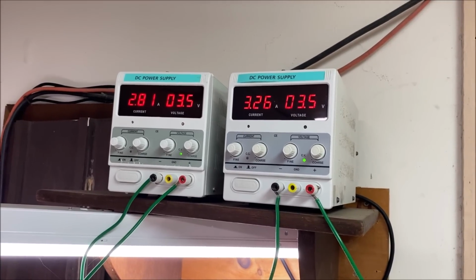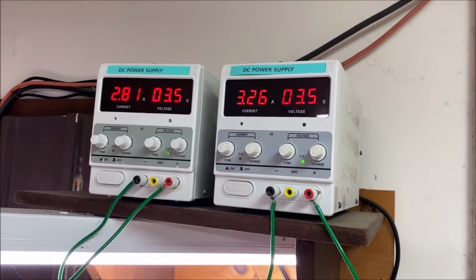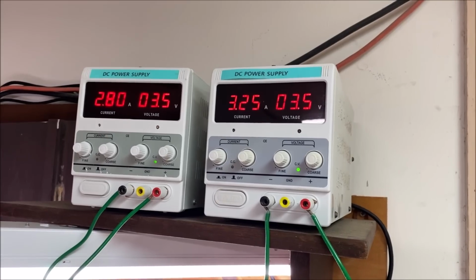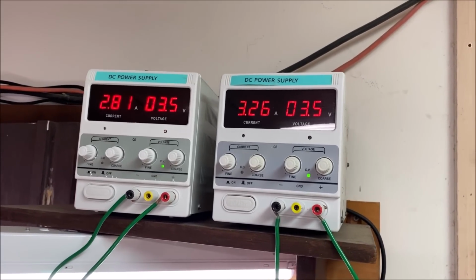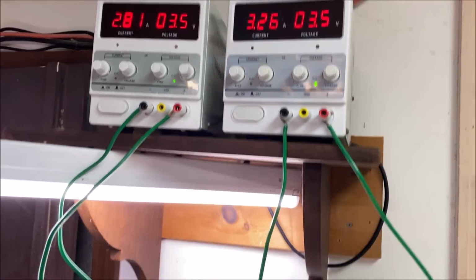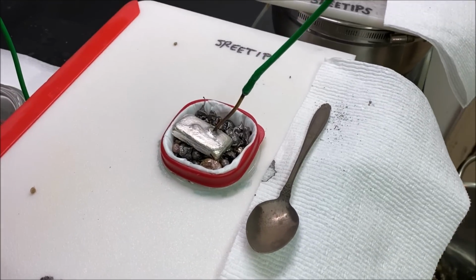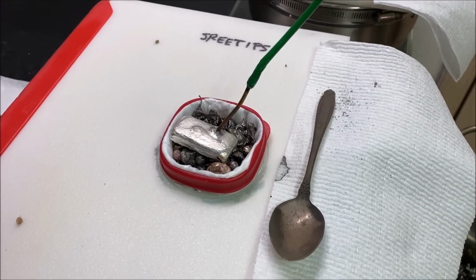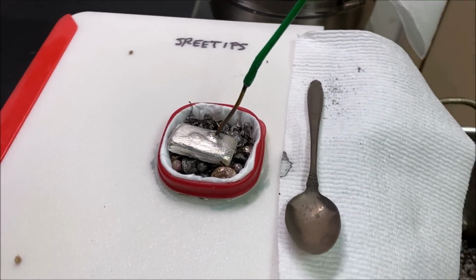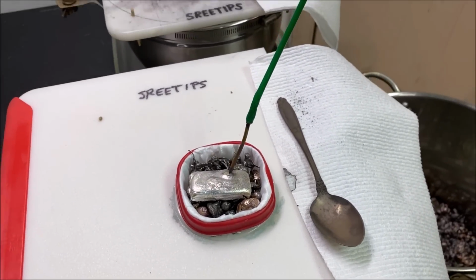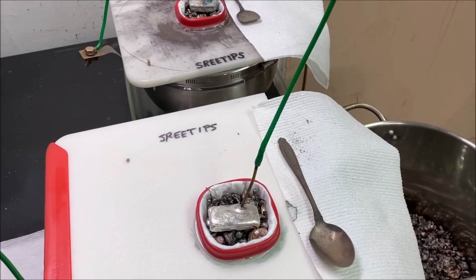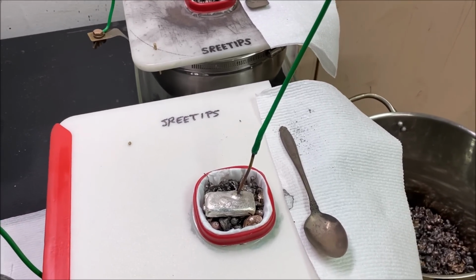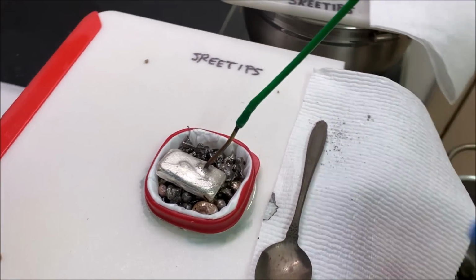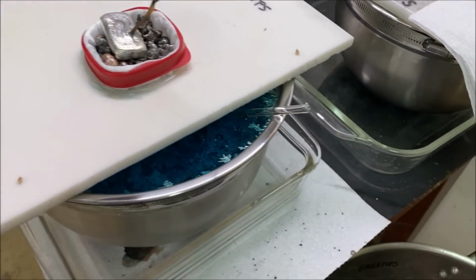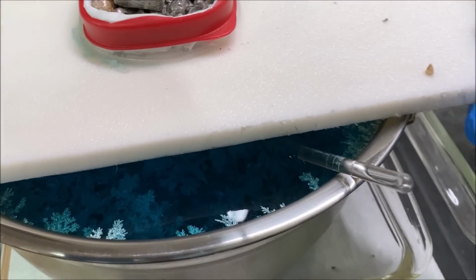Looks like we pegged out at about 2.8 amps, but that's 2 amps higher than what we started with. So the benefit of changing out that anode filter is increased current flow through the cell, and the current flow is what does the work. So that means we're going to get faster silver production in the silver cell.